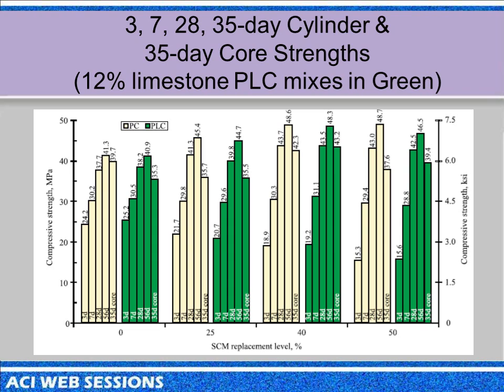These are cores extracted from the site, and of course the core strength was done late in the season. These were done in October, so these cores were extracted early December, and so of course it was cool weather out there, so you wouldn't expect the same curing. But what you see is that they're pretty much identical at all ages. In fact, even the 3 day with the Portland limestone is better than the Portland. And as you see, you add SCMs at later ages, the strengths come up even more.